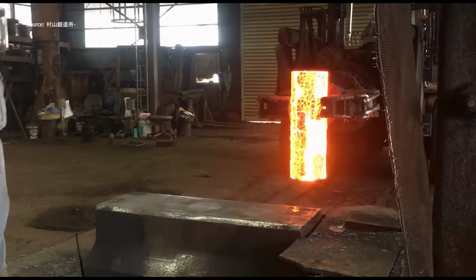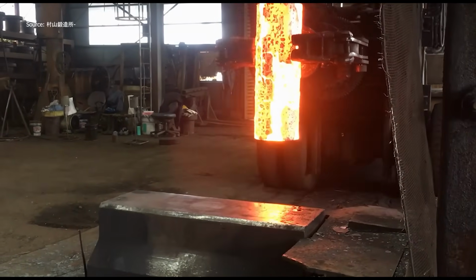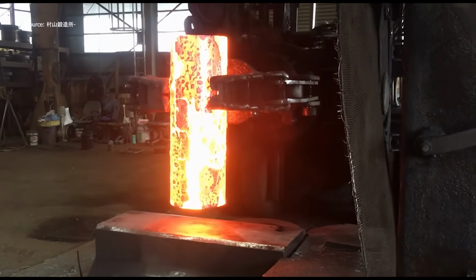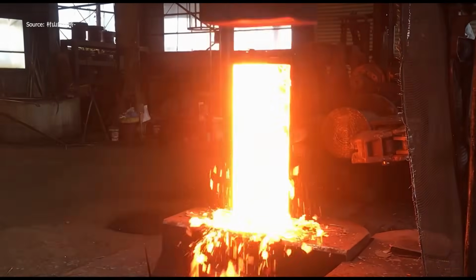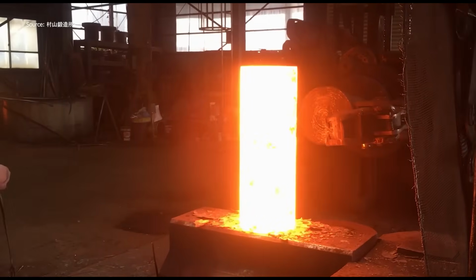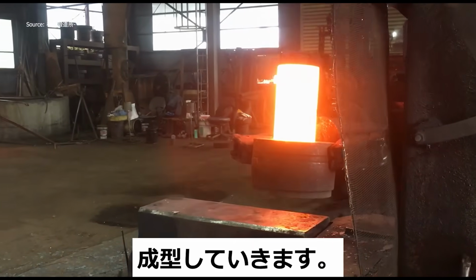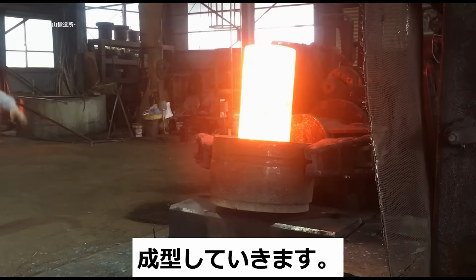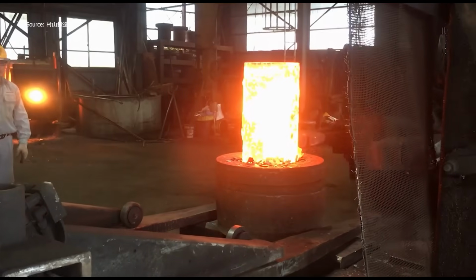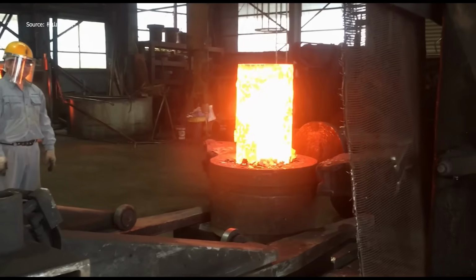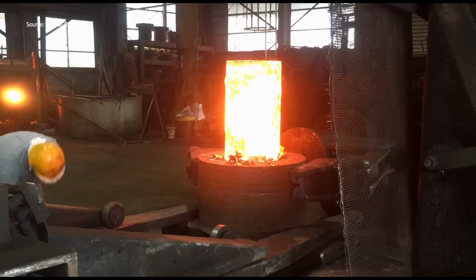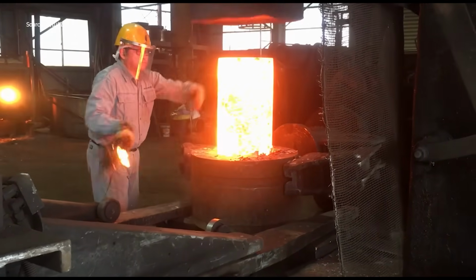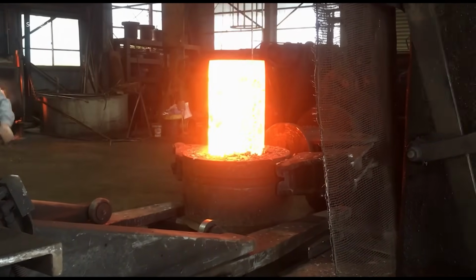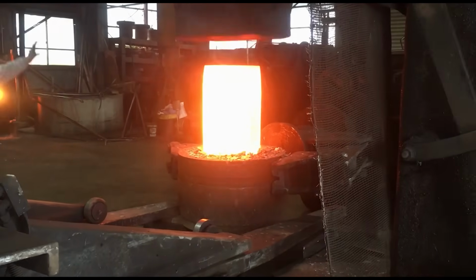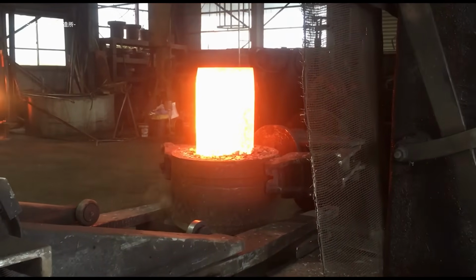From glowing steel to forged perfection, this is how a 900 kilograms coupling is born through traditional Japanese free forging. Each piece starts as a raw cylinder, its surface still coated with mill scale from prior processing. The process begins with S45C steel, a medium carbon material favored for strength and machinability. Heated until red hot, the billet is transported to the forging station.